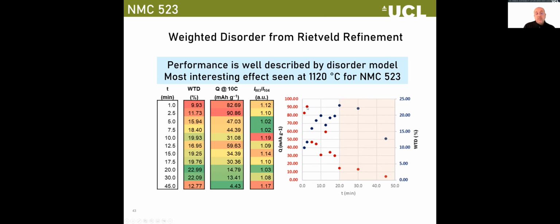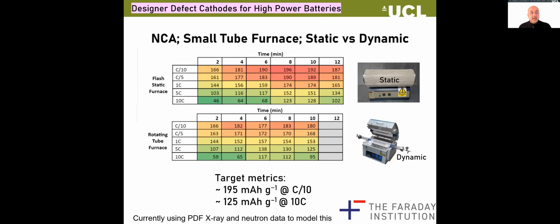So at 2.5 minutes we have a material, and if we just go down to this point here, it has a weighted disorder of above 10%. So it's quite a disordered material. It's certainly not near 2%, and it has a capacity value that is probably comparable or better in some cases than the commercial equivalent material. And I'll give you some results here with NCA. Again, I'm not going to talk about weighted disorder on this slide. I'm just going to focus on the actual capacity values.